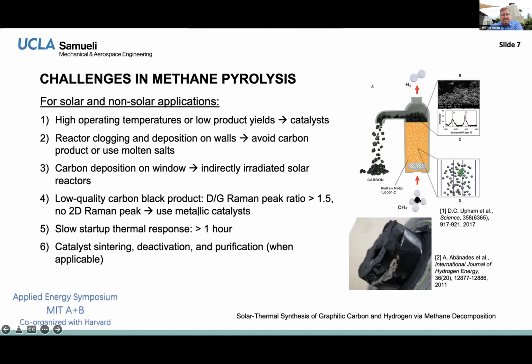an issue. But as we go down this list, methane pyrolysis, the ultimate form of carbon, is not a single thing. So most of the time, people are making some kind of carbon black, maybe with a little bit of graphitization. If they have graphitization, it's usually because they have a catalyst, right? A metal catalyst. Iron is a typical one. But then you have the problem of separating the catalyst.